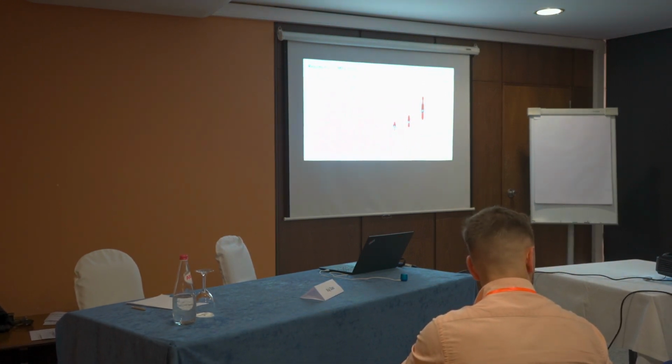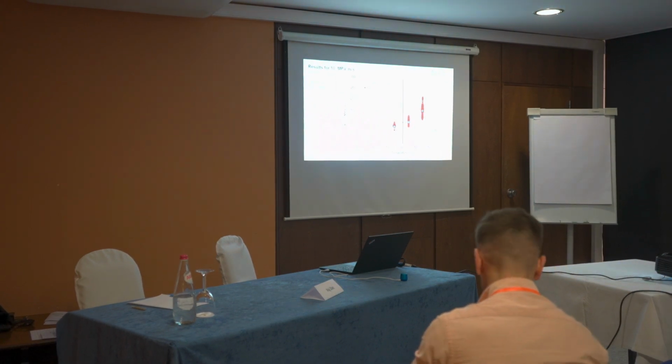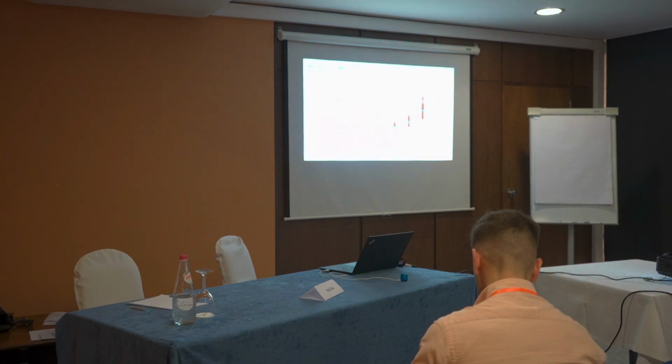What you can see is that the effect is smaller than for the 10 to the 5th, but we made a lot of tests, 30 tests at +20, and you see there is still a shift of 10 degrees Celsius, even if we don't expect much temperature increase at the crack tip. And we can show this in the distribution.